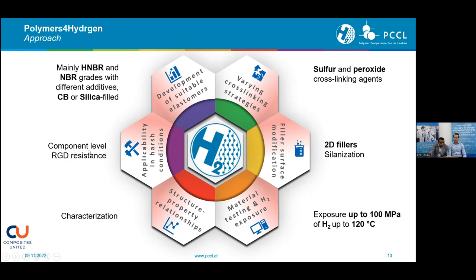Then we test them at component level, like a sealing application, to see their applicability in these harsh conditions, in terms of characterization of structure-property relationships. We have also developed test methods here, to see how materials behave under high pressure hydrogen. So we have also tested up to 100 megapascal and 120 degrees C.